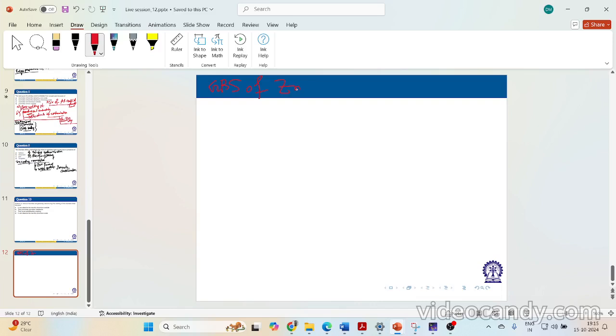So that will happen especially in the heat affected zone. Now during welding, the temperature of your base metal, which is steel, will exceed the boiling point of zinc, right? That will exceed this 900 degree C. That will cause my zinc coating to vaporize near the weld pool. And when it gets vaporized, what will happen? They will diffuse into the steel's microstructure, especially into the grain boundaries, because grain boundaries act as paths for lower energy and faster diffusion than the grain interior, right?